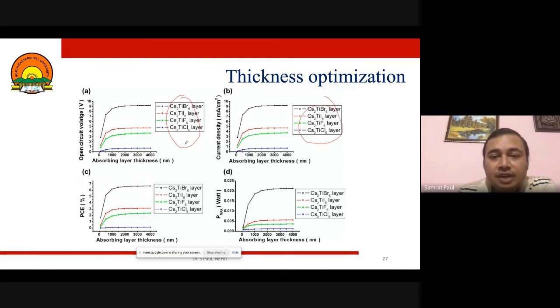And with the different absorbing layer thickness, we have calculated the current density, and we found that after some time the current density or the open circuit voltage comes to a peak, and it doesn't change much. So with this we can conclude that an optimal thickness can be used, because if we don't use an optimal thickness, or use a very thick material, it is a wastage of the material, as well as there will be more chances of recombination while the electron or hole travels through the electrode. So finding an optimal thickness is very important.